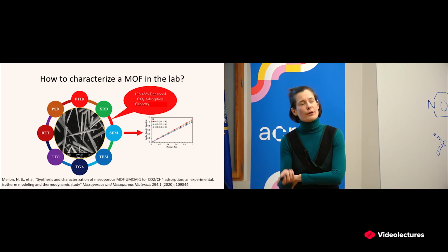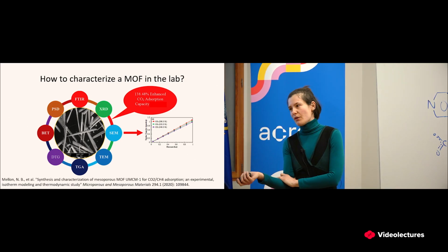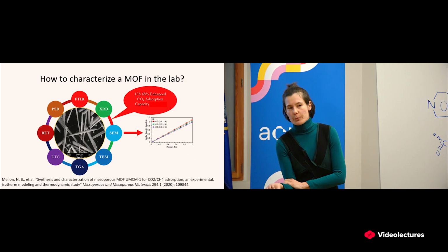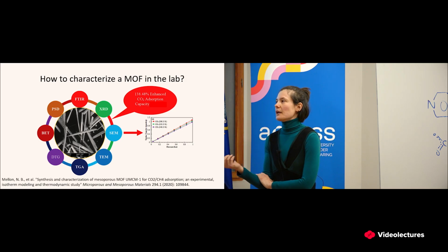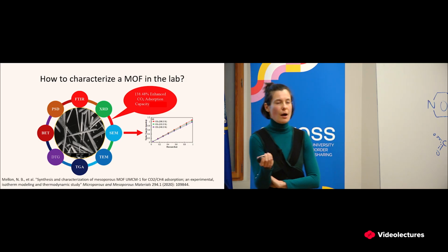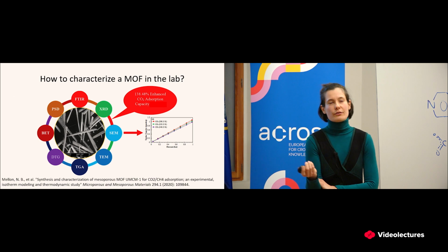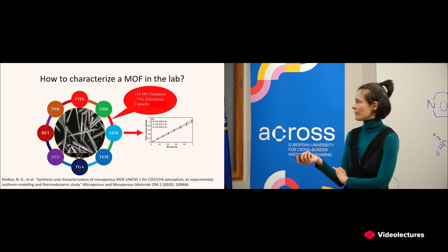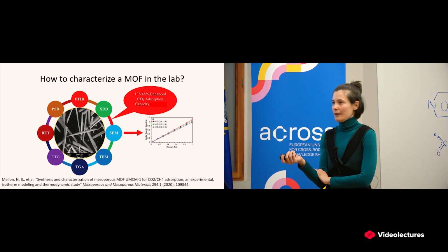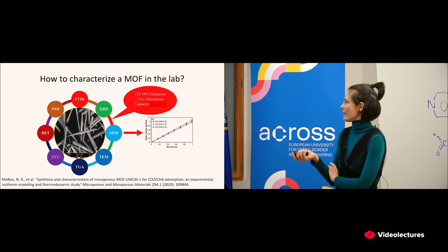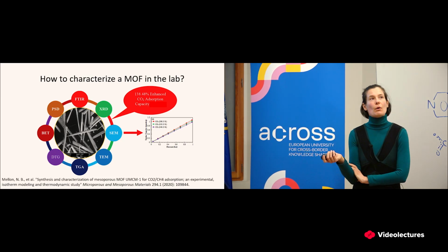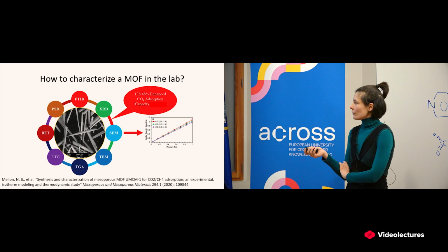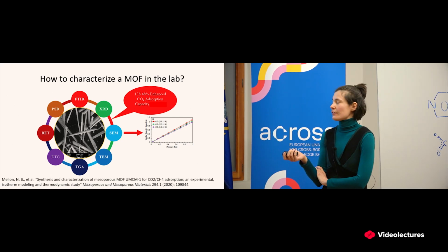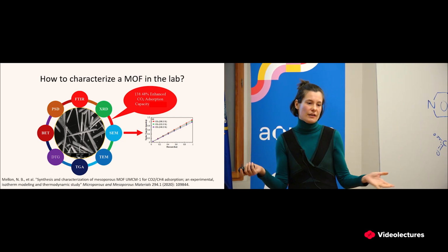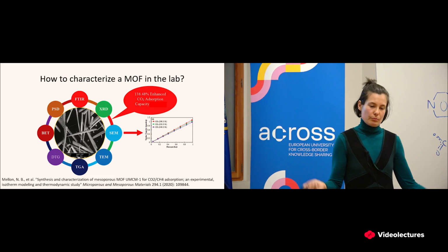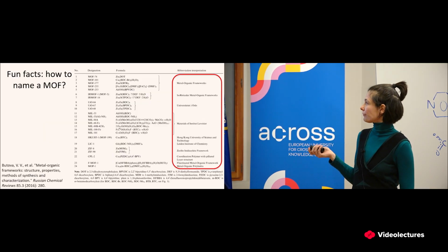I didn't emphasize this point too much, but the earlier structures of MOFs were not particularly thermally stable. And so later, when they achieved thermal stability up to, say, 300 degrees Celsius or 350 degrees Celsius, they were already happy with that. And then, of course, you also want to know how your MOFs look, so you would often do scanning or transmission electron microscopy to see their shapes, morphology, and so on.